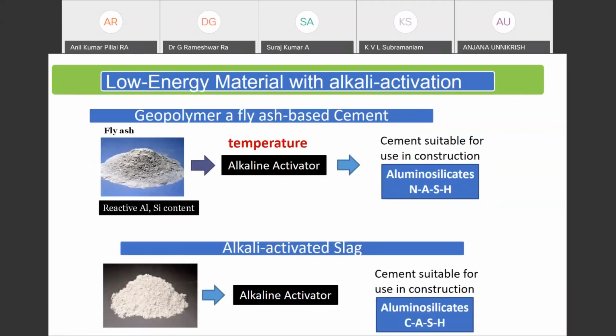And the way it works is that we start with fly ash, which contains reactive silica and alumina. We basically activate it with alkaline activators. We mix it with highly alkaline solutions of sodium hydroxide and add some sodium silicate to it. Sodium silicate is water glass, which is basically used in the manufacture of soaps. And then when you subject it to a little bit of temperature, about 60 degrees or 85 degrees curing, we're